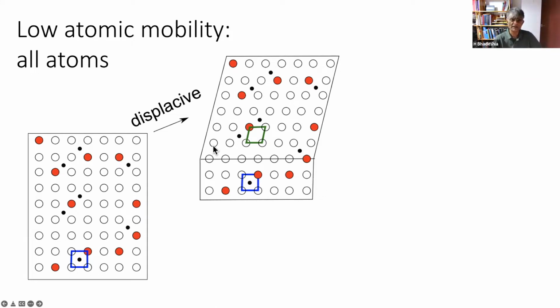But because the atoms move in a coordinated manner, you get this shape deformation, which is really quite large, actually. It's a shear strain of the order of 0.26, which is much, much bigger than a typical elastic strain, which is 10 to the minus 3. So imagine that this is pushing against all the other crystals. Then this will be a strain energy dominated transformation. Many of the features of the transformation product will depend on the accommodation of the strain energy.